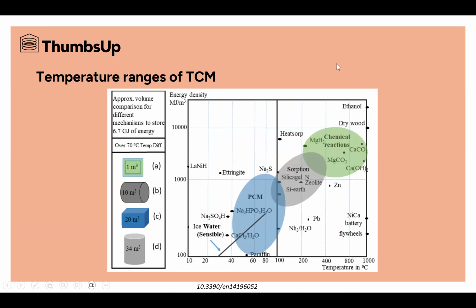In particular, just to see the temperature range of the TCM, in our case, we have absorption materials. So for the charging phase, we have a range of temperature between 150 Celsius degrees to 80 degrees, more or less. While for the discharging phase, the range of temperature of discharge is between 50 degrees and 10 degrees.